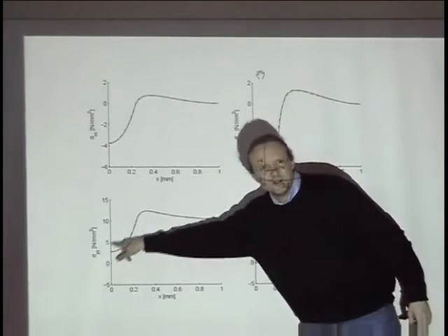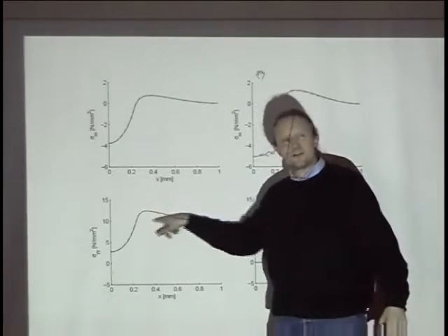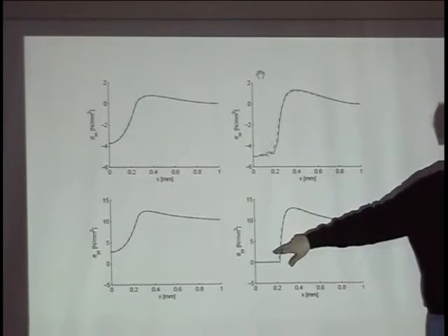There are some spurious vertical normal stresses which shouldn't be there. That's because you solve the classical elasticity equations separately from the gradient enrichment, and the gradient enrichment doesn't know anything about traction boundary conditions, so it just smooths the whole thing out. Which is fine, you should get rid of the singularities, but you also get some funny non-zero stresses where it really should be zero. So in that sense you can argue this is more realistic.